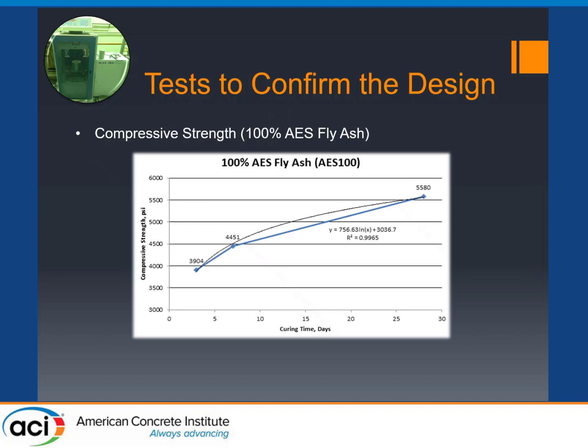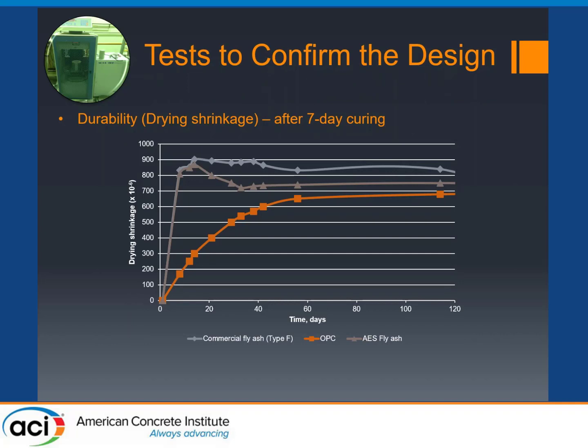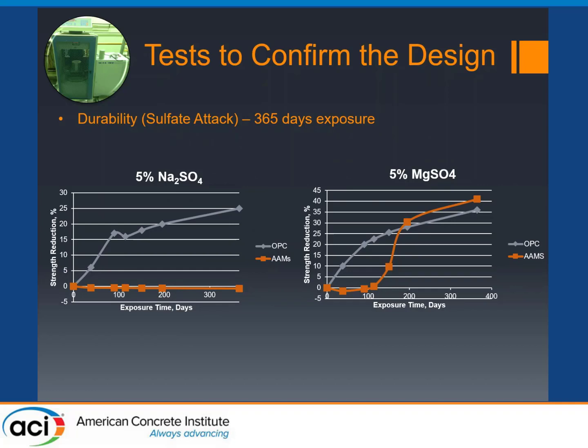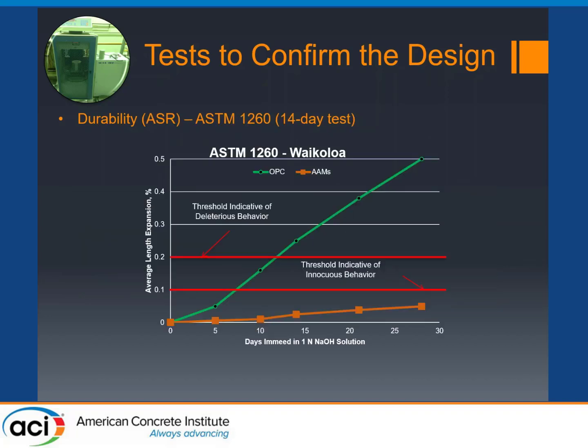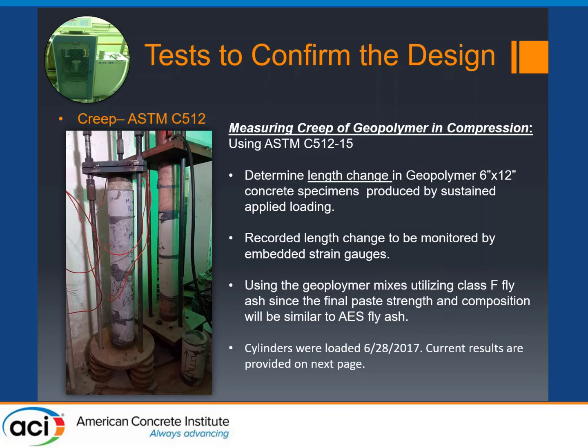Workability and slump can be well controlled. Strength, satisfactory. Again, it is very easy to achieve high strength for this type of concrete. The hard part is how we can satisfy all fresh and hardened properties, as well as durability, safety, and cost. Drying shrinkage, pretty much similar to normal OPC. This is sulfate attack. It is pretty much immune to sodium sulfate, but similar to OPC for magnesium sulfate, because we know it generates CSH, which could be attacked by magnesium sulfate. ASR, pretty much immune to ASR problems, which is again consistent with other research. Creep, similar, no surprise here.